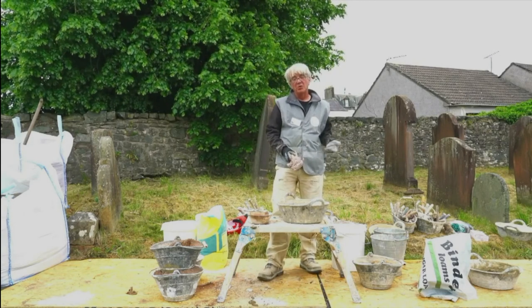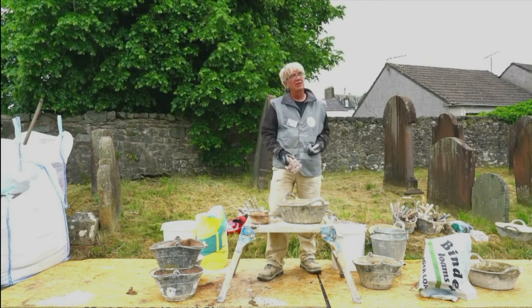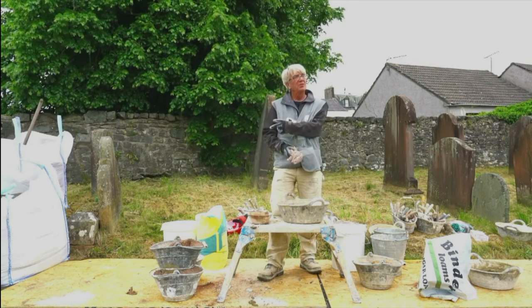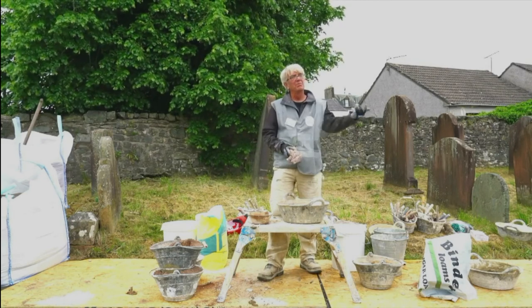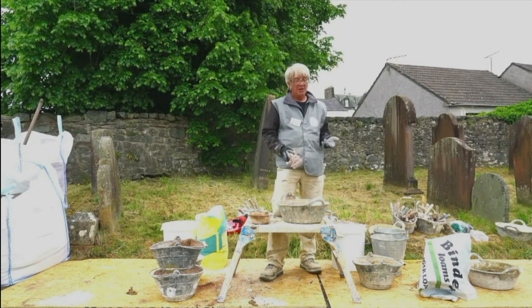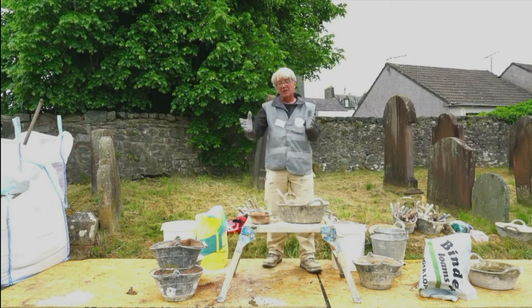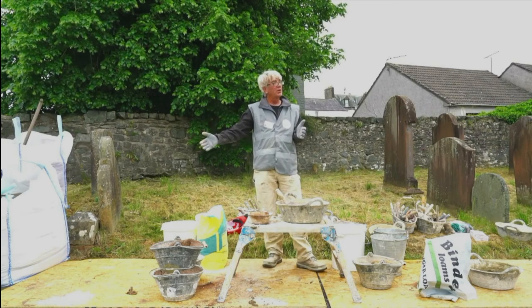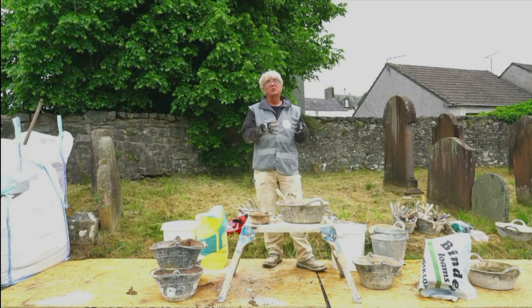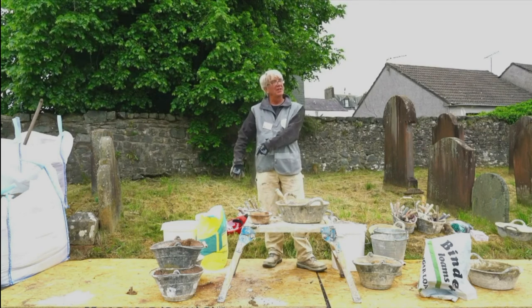As far as one of the things that was said a lot as well, oh yeah, but you know, you can't do this on a modern building site. It is, but if we're using a mixer, what's the difference between mixing that and making a mortar than putting NHL or cement in? What's the difference in time, in everything else? There is a difference in time, which is the best practice with NHL says you should leave that mortar mixing in the mixer for at least 20 minutes. This one, as soon as it's made, you have it out. As soon as that's all together, so it's 5 minutes to make a mix.